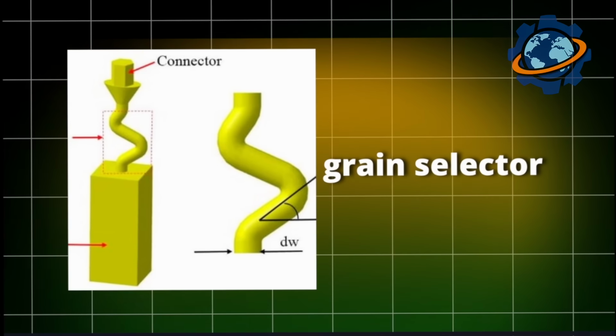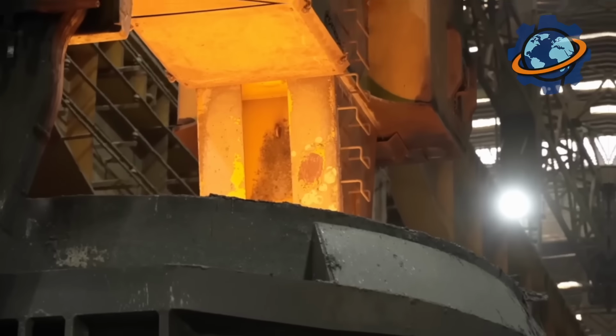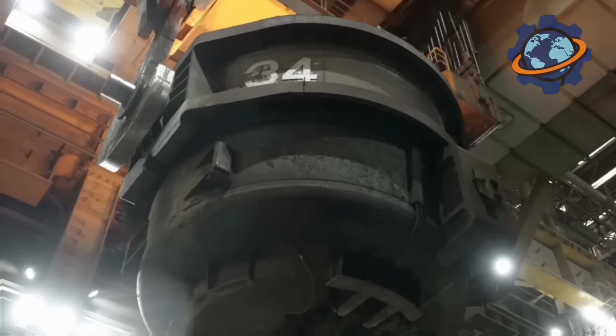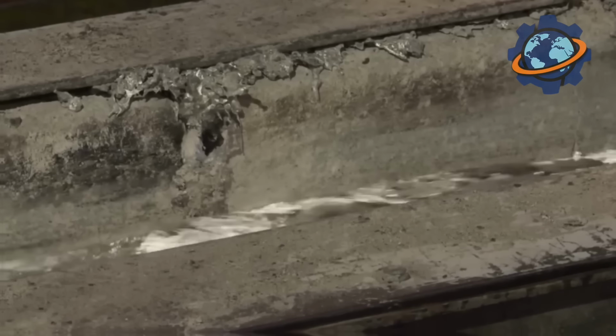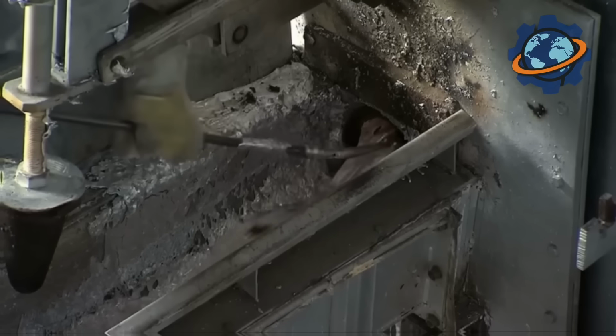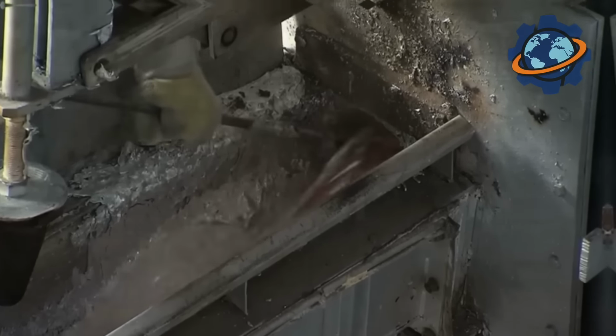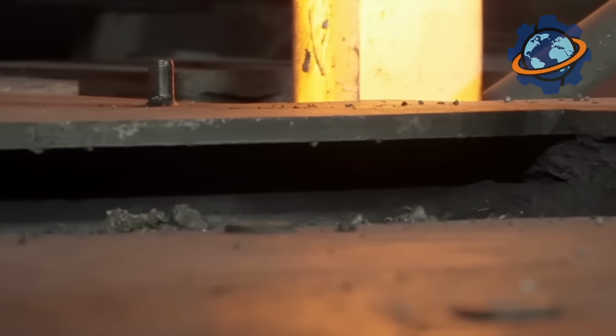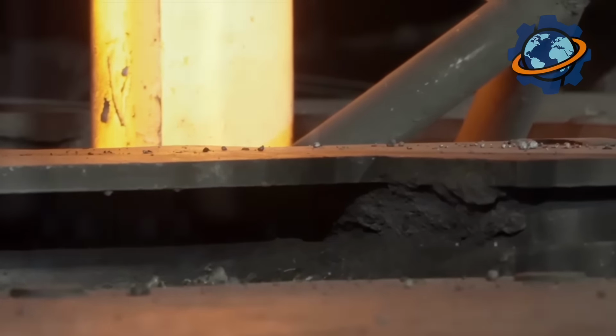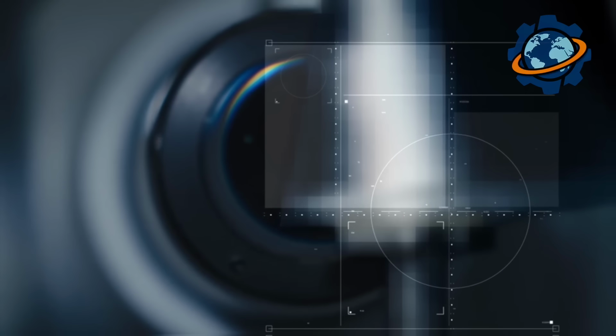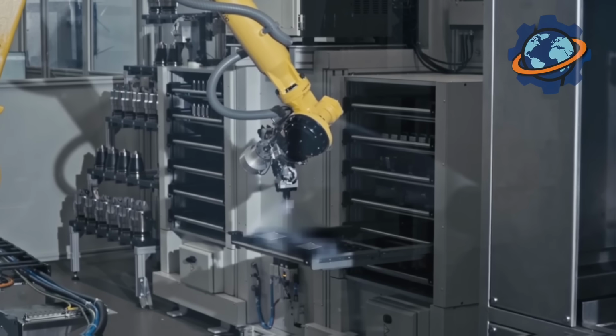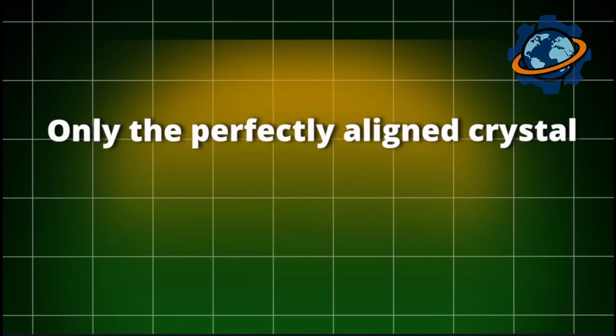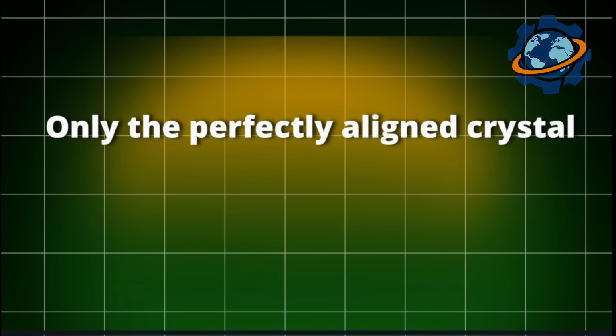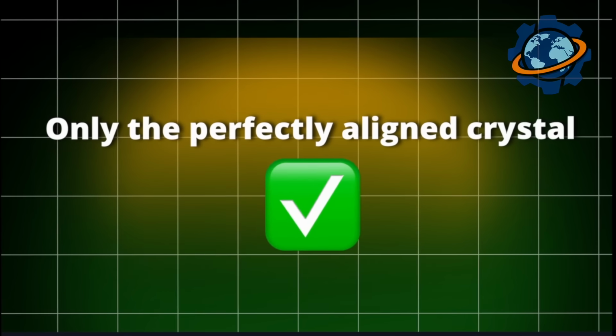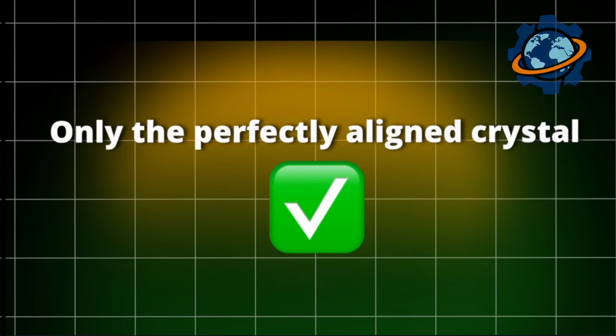At the mold bottom sits a grain selector, a corkscrew-shaped passage so narrow only one crystal nucleus fits through. As metal solidifies upward, countless tiny crystals form at the chill plate. They compete, growing upward like metallic trees racing toward sunlight. Most hit the spiral walls and stop. Only the perfectly aligned crystal, the one matching the spiral's orientation, passes through this metallurgical gauntlet.